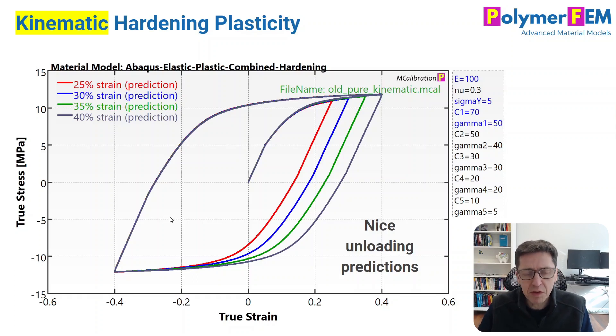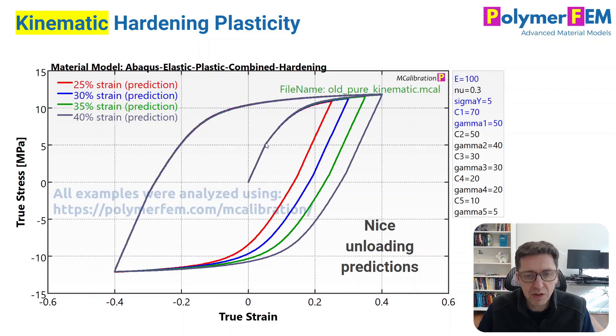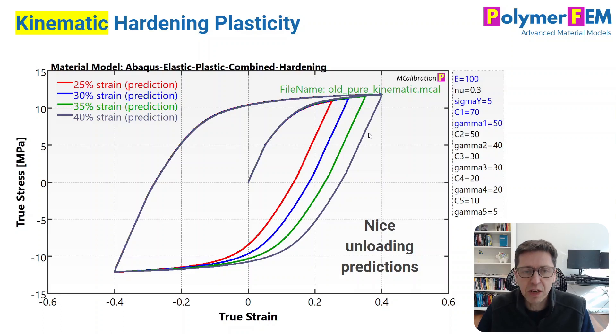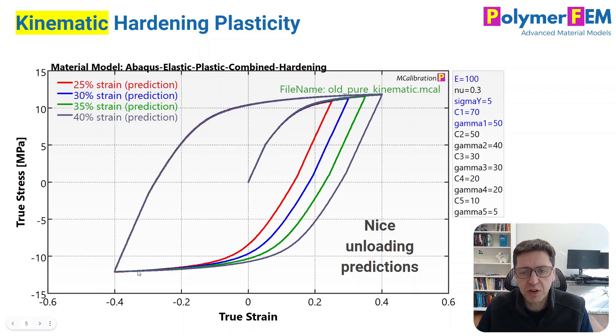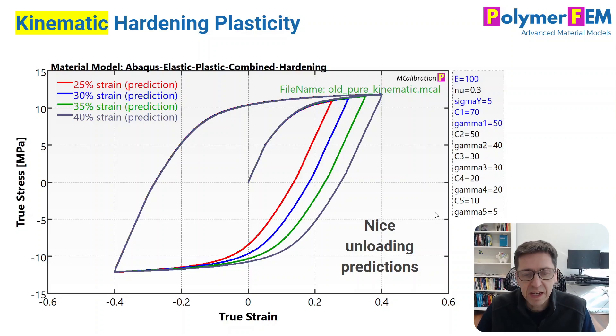The way to overcome this is to switch to kinematic hardening, or perhaps combined hardening. Kinematic hardening is a little different — you load up to the point where plasticity starts and the curve rolls over, then you unload and the reverse plasticity starts at about twice the initial yield stress. You get much nicer, more realistic unloading predictions, similar to what we see when we test thermoplastics. This is a multi-network back stress kinematic hardening plasticity model.